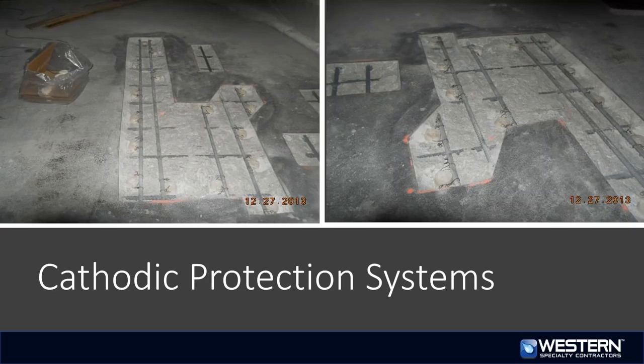Okay, I previously mentioned the cathodic protection system, and if you look close in these pictures, you can see these little round, kind of greenish discs that are wired to the reinforcing steel. These little discs have a zinc puck within, they're coated, but they have a zinc disc in there, and they're connected to those wires that are then connected to the reinforcing steel. The reason they put those in is so that as moisture and air and so forth gets to the reinforcing steel, you have this electrolysis process that takes place. That's what typically would corrode the steel. And when the reinforcing steel corrodes, that's what causes concrete to spall.